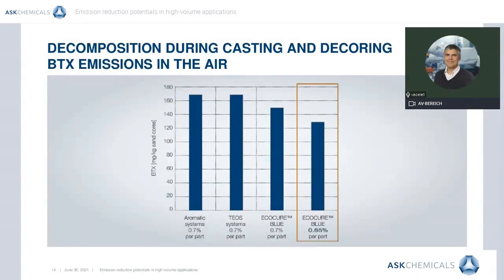The results presented here and on the next slides were measured in the USA using a method called Woodstack, specifically developed by ASK, formerly Ashland, which is probably the most reliable method currently available. Each value presented in the slides is the average of a minimum of 3 gray iron casting tests.